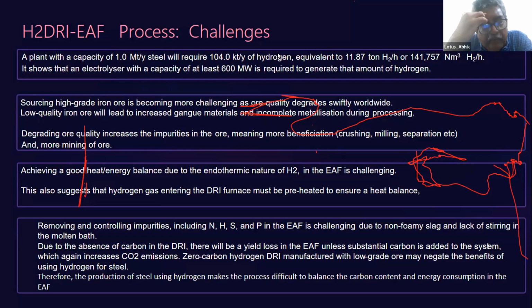So there's no problem with that in the main BF-BOF route or the DRI-EAF route where coal is charged. Coal and coke, carbon, is charged. But that is not happening with hydrogen. The characteristics of the slag change because of this hydrogen-based extraction. What happens is that the slag gets dissolved in the iron. So it's very difficult to remove the slag impurities from the iron itself, right? So it is saying that removing and controlling impurities like hydrogen, sulfur, phosphorus is challenging due to the non-foamy slag. Basically, it is not separable. It remains included in the hot metal itself.